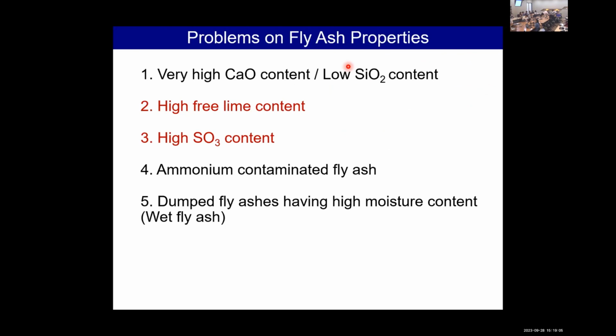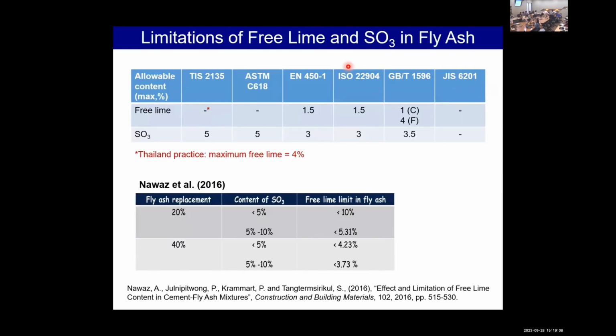Next problems are high free lime content and high sulfur trioxide content. This table shows the limitation of free lime and sulfur trioxide content. For free lime content, the TIS standard has no limit. But in practice, we control the maximum free lime content to 4% based on our previous study. For other countries, the ASTM or Japanese standard, there's no limit as well. Only the EN, ISO, or Chinese standard limit the free lime to 1 for type C and 4 for type F.